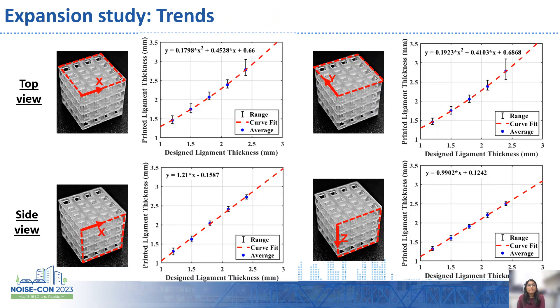Based on the ligament thickness dimensions captured from all the 3D printed samples, we extracted the trends in each direction on the top XY plane and the side XZ plane. In agreement with the optical analysis, we see that the as-printed value is greater than the design value. We approximate this trend using a quadratic fit shown by the red dashed line. The blue dots show the average dimensional measurements in each direction, and the range indicates the associated standard deviation. Overall, the expansion rates along the X and Y directions are larger and very similar to each other, while smaller expansion rates were observed along the build direction.